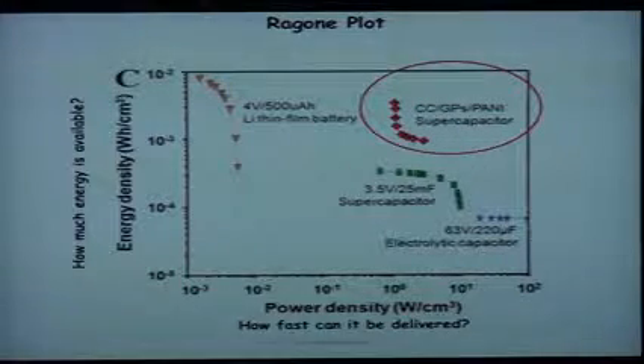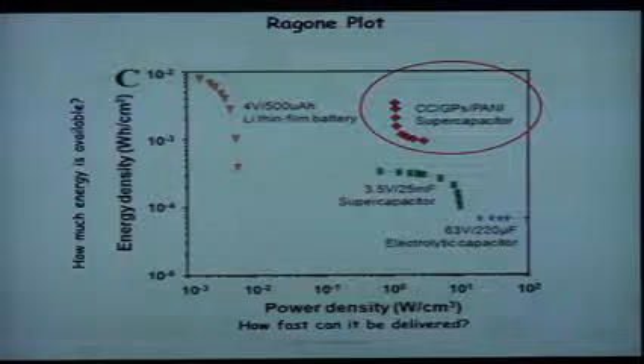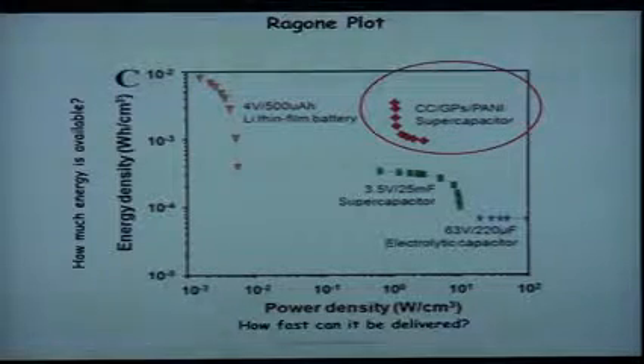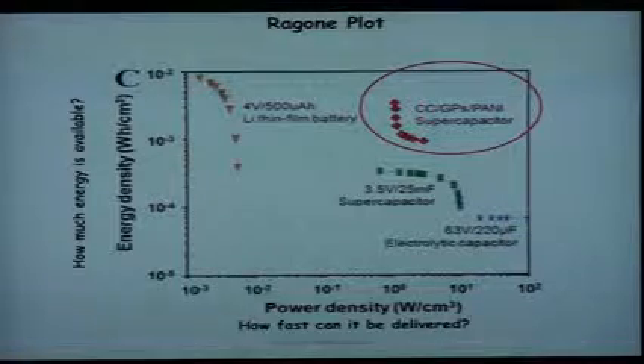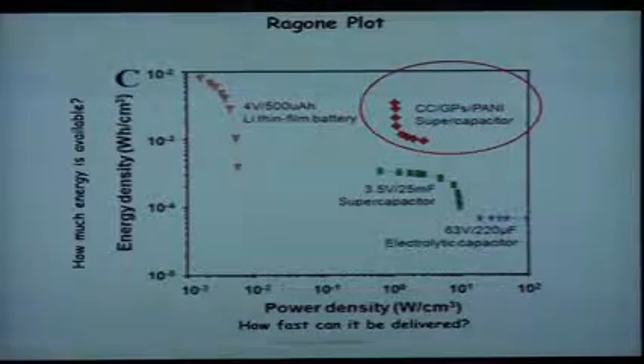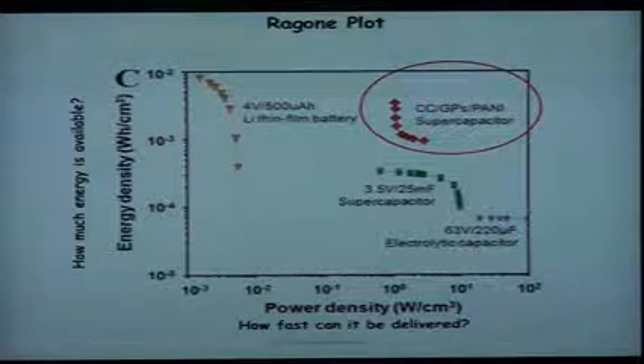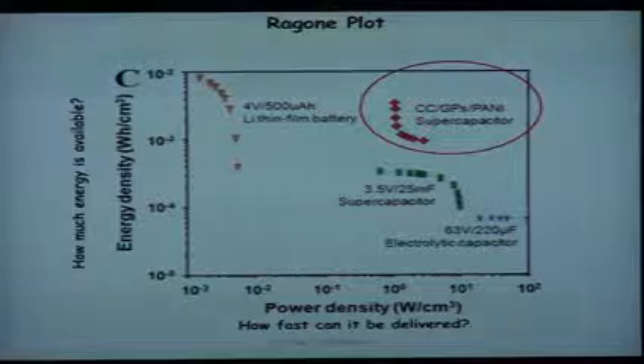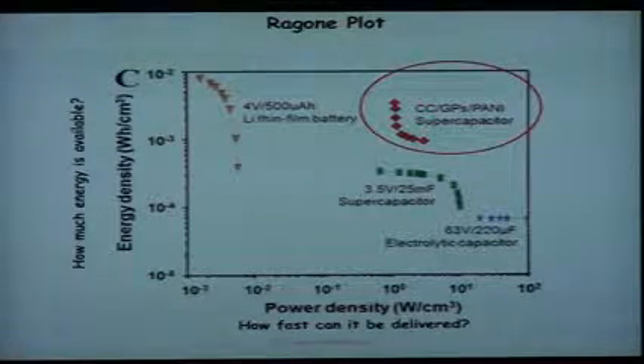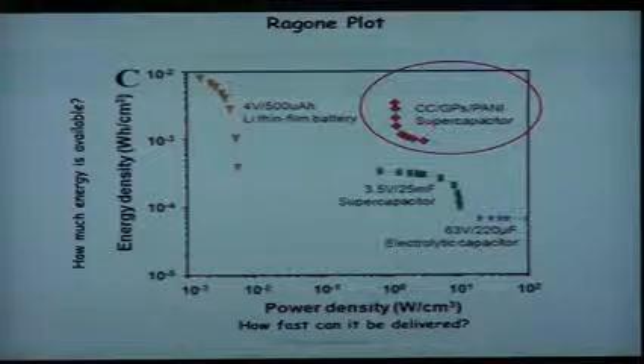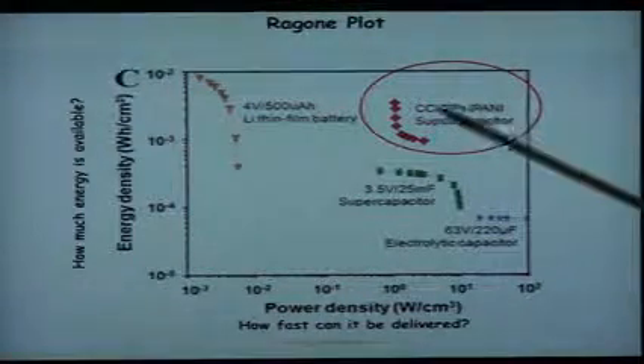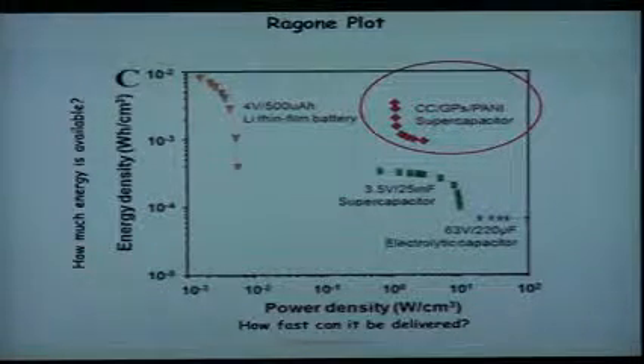So back to our Ragone plot. Here we have energy density on the vertical axis, power density on the horizontal axis. This is a volumetric basis. And if you look at this performance relative to thin film lithium-ion batteries, this is not your typical lithium-ion batteries, and other supercapacitors, including an electrolytic capacitor, you see that in this case the power density is high and comparable to what you get in these other comparative supercapacitors or just capacitors, but the energy density is much higher than those capacitors and comparable to what you would get in this thin film lithium-ion battery.